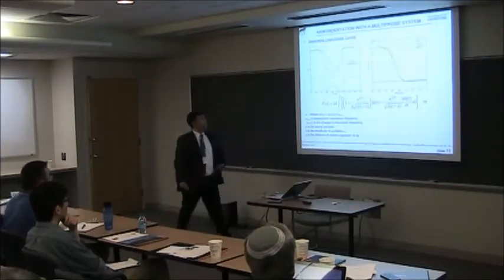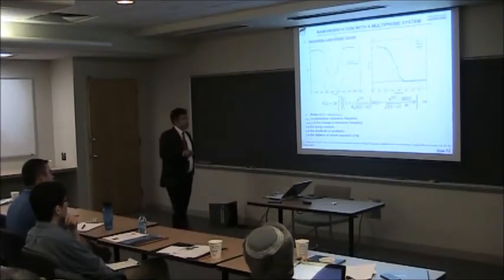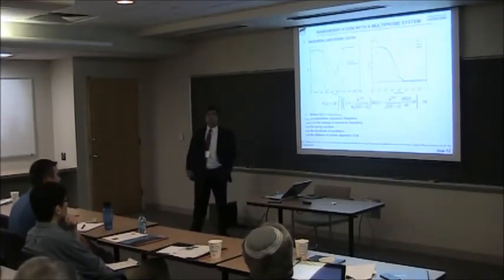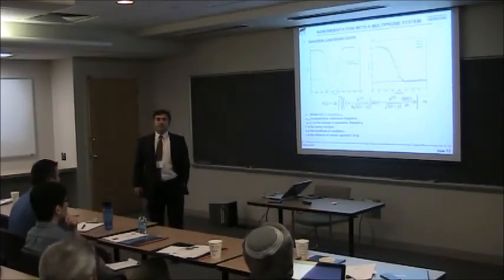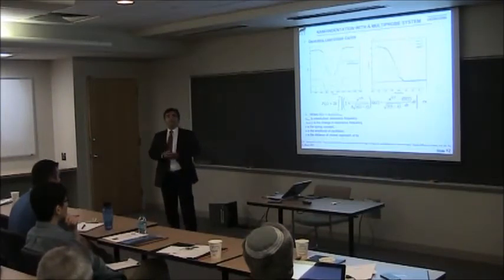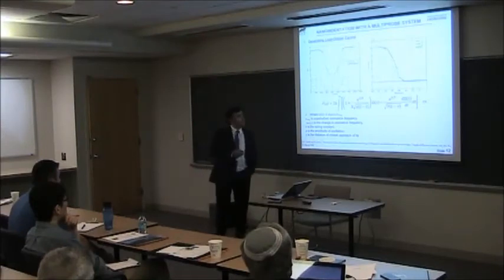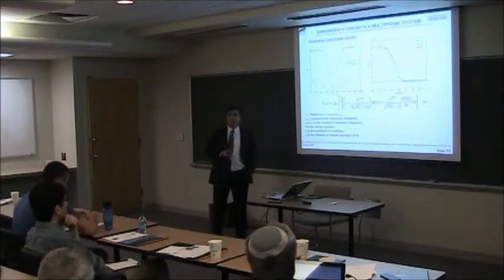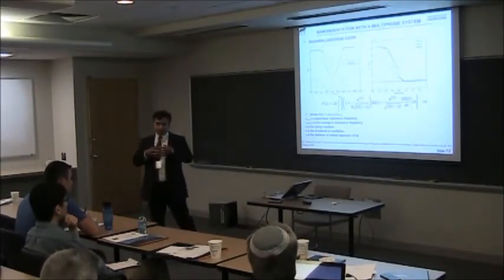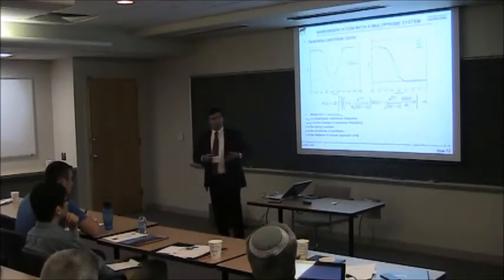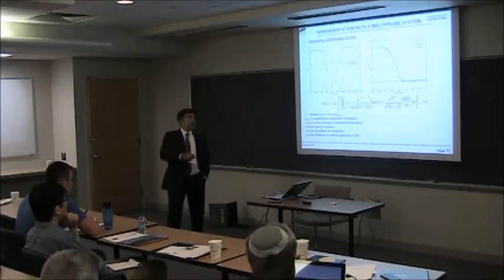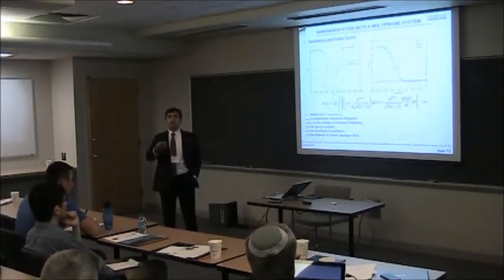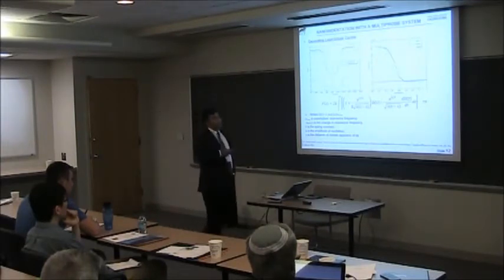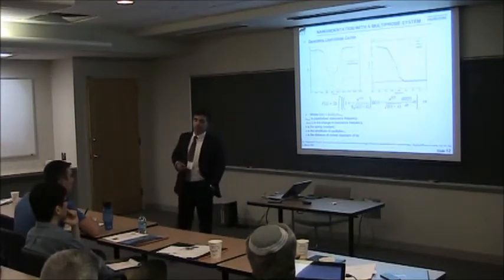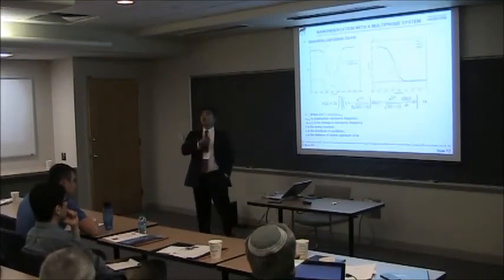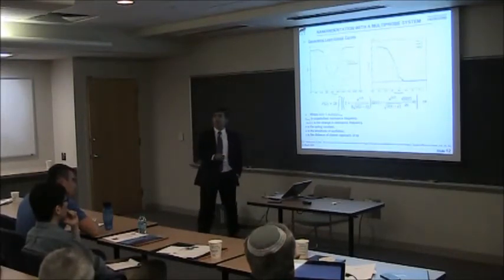And as Kit was saying, the Nanonics tool actually calculates the force through this formulation. And it's not like F equal to Kx, right? It's different. So it's good and bad at the same time, because since they are all mingled together, you don't have a separation. So in a way, we are trying to create that separation. While doing the indentation on a known sample, if I can make sure that this force reading is accurate enough, and then while measuring the actual displacement, I may use the Oliver-Pharr model and other models a lot better, using the force value and the displacement, rather than just depending on whatever I read.